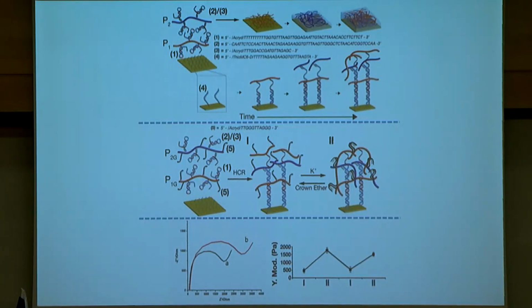This is not yet a smart film. To convert it into a smart film, we attach to the polymer chain additional nucleic acids that include an element of information to be smart. For example, once we take this polymer, we may induce the hybridization chain reaction, and we make the hydrogel on the surface. If this tether is G-enriched, we know already that it will form a G quadruplex. We will cross-link, in the presence of potassium ions, the surface not only with the duplexes, but also with the potassium G quadruplexes. And then we get a relatively stiff hydrogel. If we add crown ether, we can separate the G quadruplex and get a hydrogel of lower stiffness. So this is the method to control the stiffness of a hydrogel interface on an electrode support.